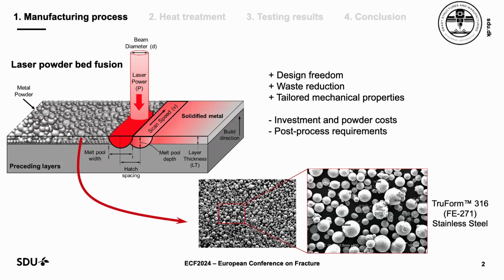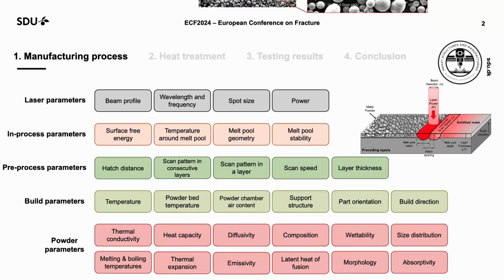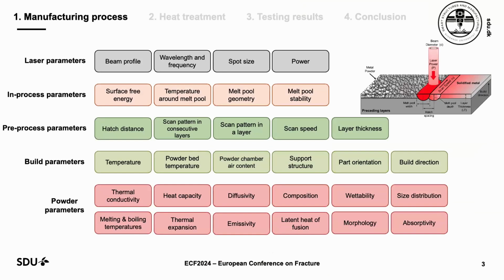There are different parameters that we can categorize, for example, laser, in-process, pre-process, build, and powder parameters. Each one of these parameters affects the part's quality, either the microstructure or the surface quality and so on. Previously, we evaluated the spot size, diameter, and the laser power. We also evaluated the scan pattern in a layer, scan speed, layer thickness, and build direction in order to characterize the mechanical property of produced parts for different alloys.